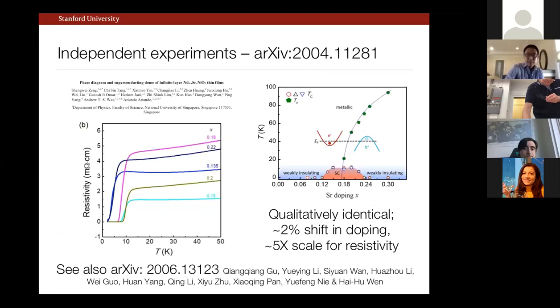So yeah, let me also mention that recently some important papers have come out on cond-mat. Independent groups have experimentally observed a very related phenomenon. The first paper that I'm aware of is, what is this, in April from a group at the University of Singapore. There's quite a bit of work actually that they did. And basically what they did in this first paper was the entire superconducting dome, just as I presented to you. Hall coefficient, many of the details are quite similar. I didn't mention it before. I don't know what the significance is yet, but they also see this strange dip in the superconducting dome.